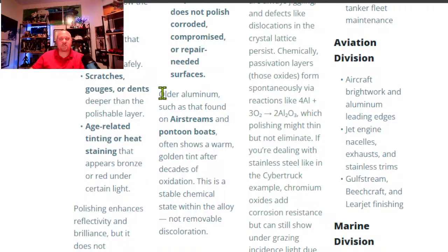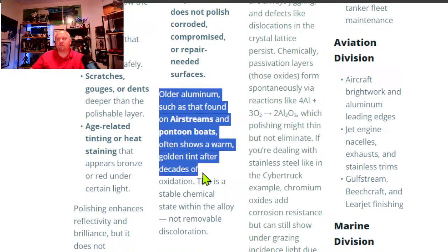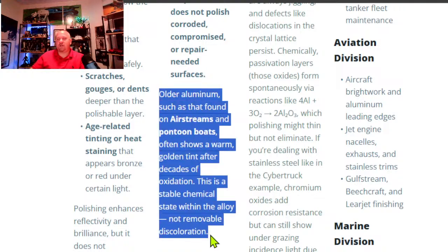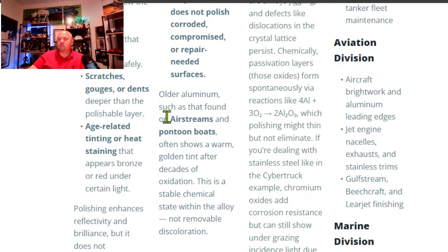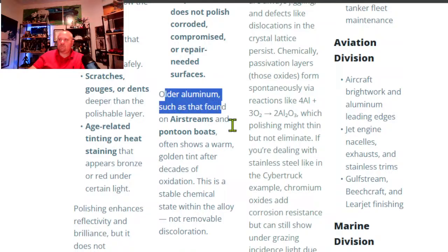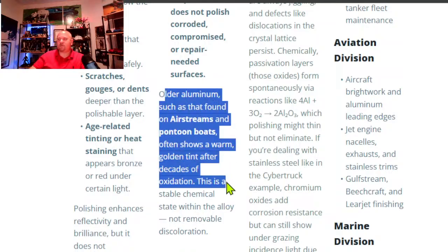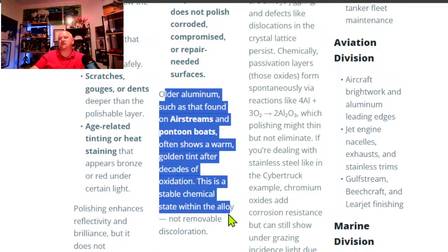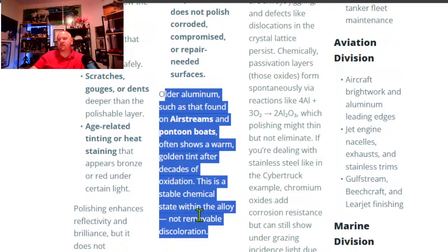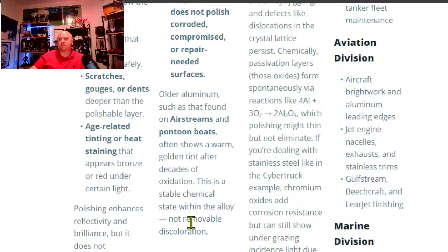It can't be done if it risks compromising something even more. Let's say an Airstream, for instance, is completely thinned out from being sanded by people stripping the clear coat 20, 30 years ago, and the surface is just rough to the touch. At that point, there's nothing that can be done. Nothing. We're not going to sand it because it's just going to thin the metal. Older aluminum, such as that found on Airstreams and pontoon boats, often shows a warm golden tint after decades of oxidation. This is a stable chemical state within the alloy, not a removable discoloration.